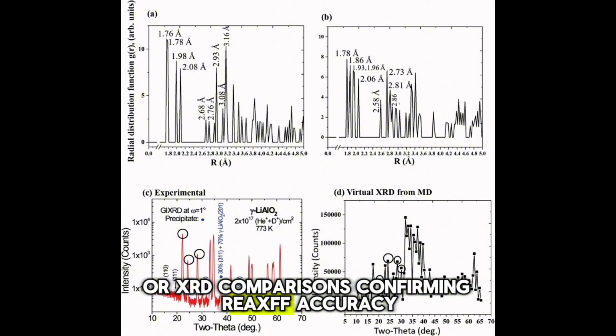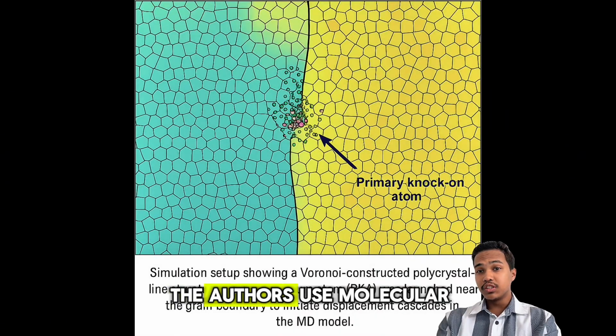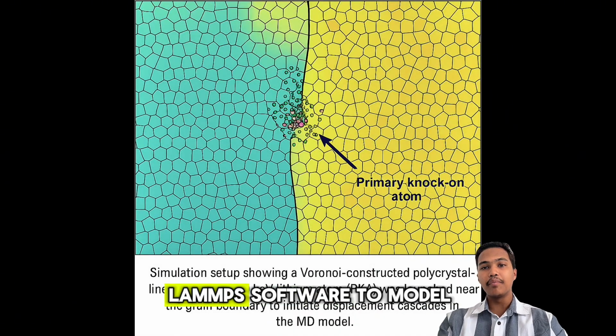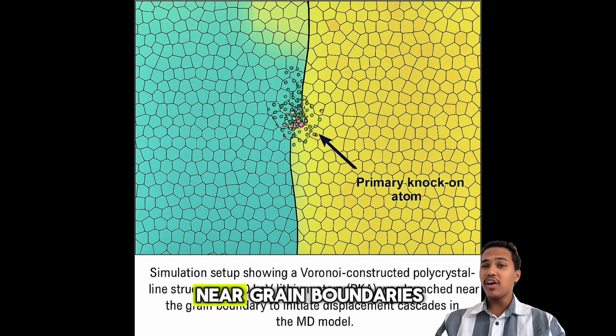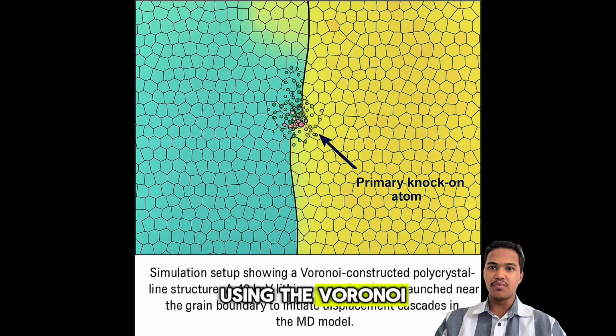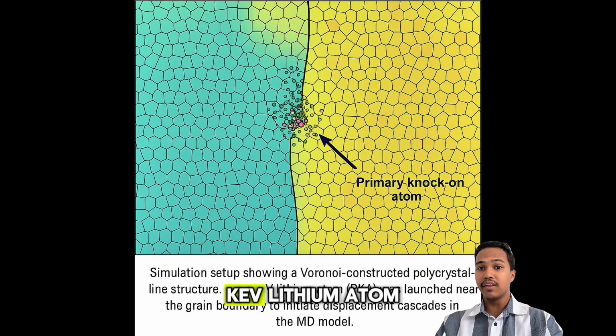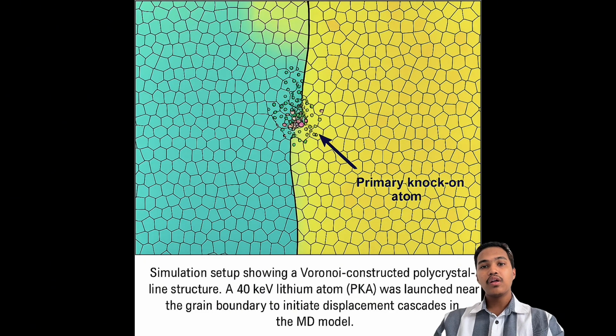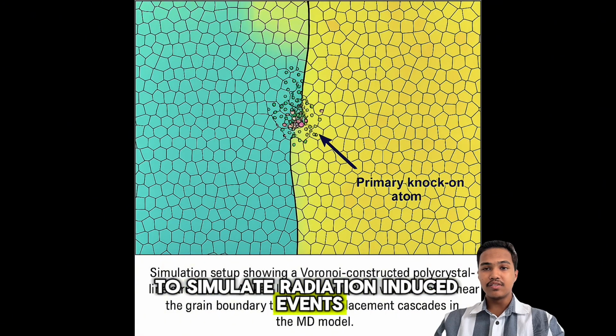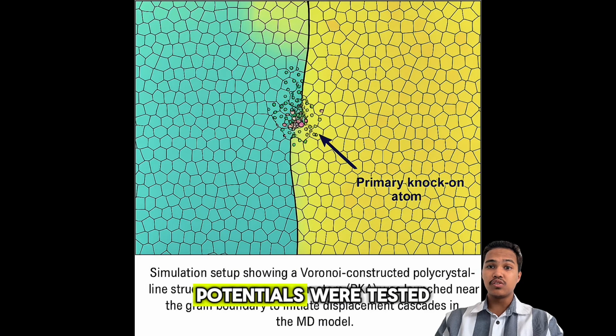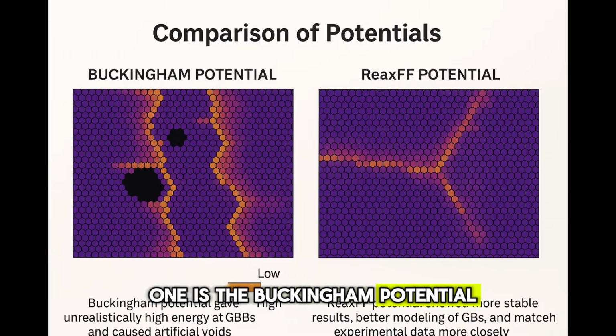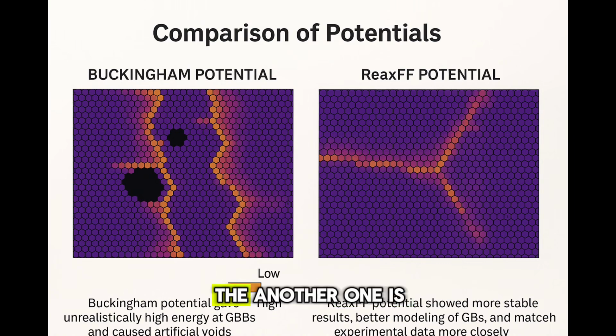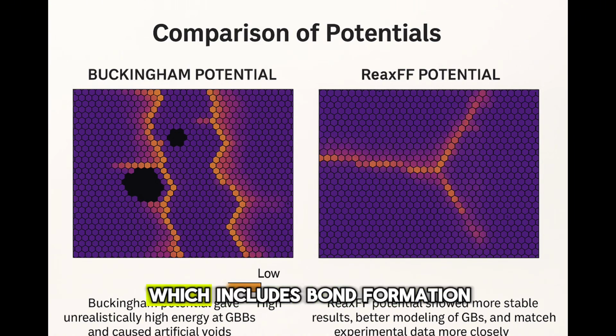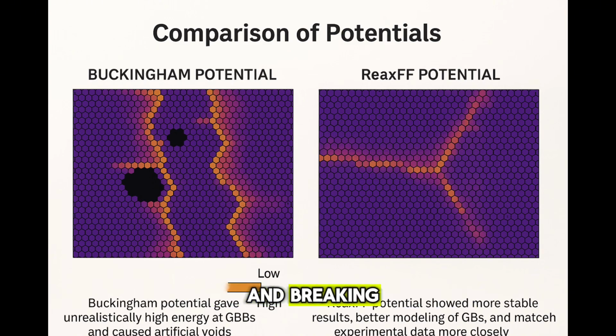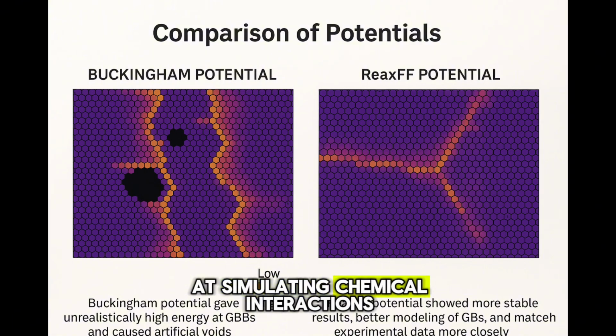The authors used molecular dynamics simulations with the LAMMPS software to model displacement cascades near grain boundaries. They created grain structures using the Voronoi tessellation method and introduced a 40 keV lithium atom as a primary knock-on atom to simulate radiation-induced events. Two types of interatomic potentials were tested. The first is the Buckingham potential, which is simpler but less accurate at modeling grain boundary behavior, and the other is a more advanced ReaxFF potential, which includes bond formation and breaking, and is better at simulating chemical interactions.